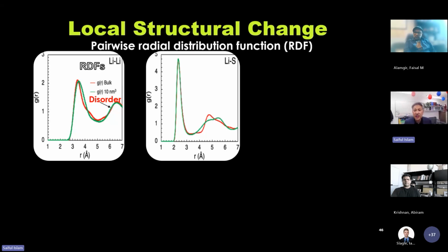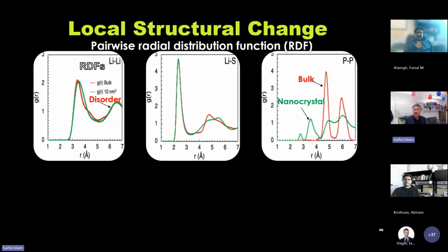In the middle there is the lithium sulfide RDF. Again, green is the nanocrystalline material, and red is the bulk. Very similar, but the subtle difference is there's greater disorder for the nanocrystalline material. But what's interesting, this is the greatest one. If you look at the phosphorus, and even the germanium, the bulk material in red is quite ordered. However, the nanocrystalline shows incredible disorder, very different from the bulk material.